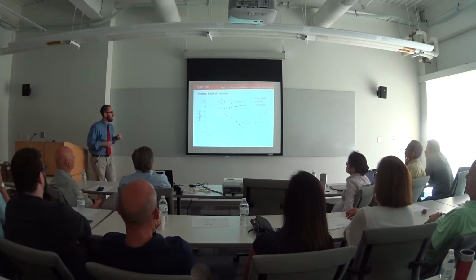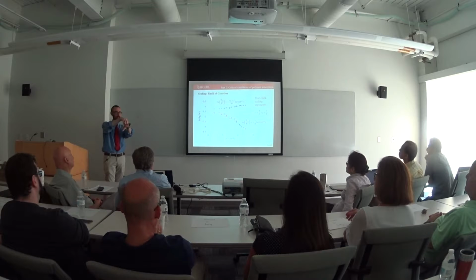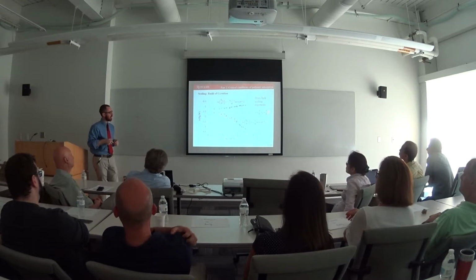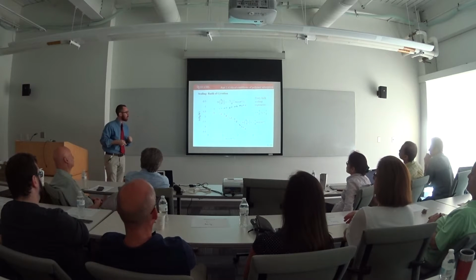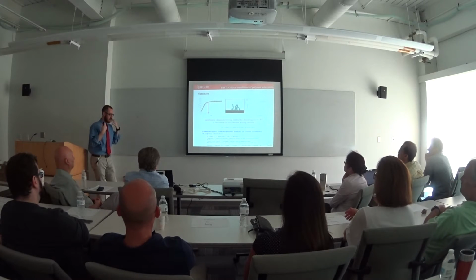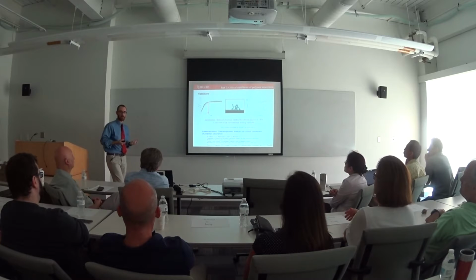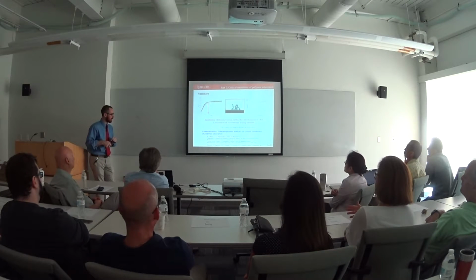I also looked at the radii of gyration, which are basically, if you have a chain, you can determine what the perpendicular and parallel radii of gyration are, and they scale with these things called the Flory exponents, which are given by these equations. And again, this proves that we have in fact found the critical condition appropriately. So in summary, in this first part of the work, I introduced a new method for assessing the critical point of adsorption of simple polymers adsorbing to surfaces. This was published in 2013 in a short communication.